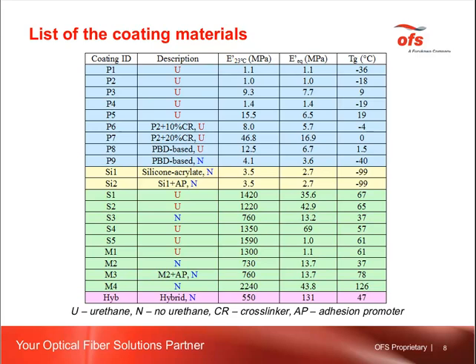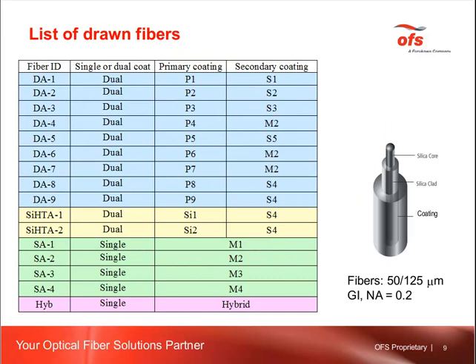The third, fourth, and fifth column of this table shows the storage modulus at room temperature, equilibrium storage modulus, and the glass transition temperature. Briefly looking at these columns, you can see a very strong variability of properties, so it was interesting for us. Do these properties cause any effect on thermal stability or maybe on other properties of optical fibers? Primary and secondary coatings were combined together, so we drew a few fibers with dual coatings, and this is shown on this table on the left.